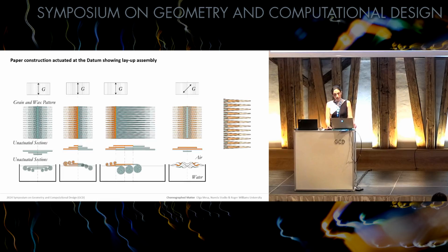So a movement from flat to convex is obtained if the wax-treated side is facing downward and the side facing upwards absorbs the water. Therefore, by tapering the boundary of the flat pattern, this can puncture the surface of the water as they actuate, thereby enabling bending downwards towards the water. We can see these behaviors in a bit more complexity in the next video, and I meant it to emulate growth.